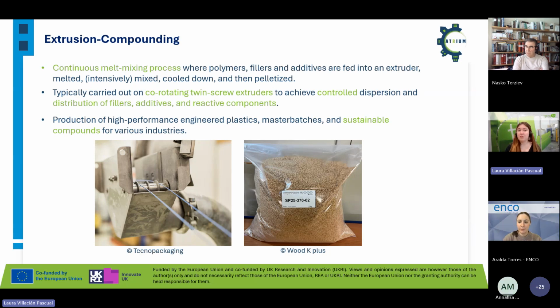So a little introduction to extrusion compounding. Extrusion compounding is a continuous melt mixing process where we have polymers, fillers, and any additive that you can imagine. And those are fed into an extruder, afterwards melted by applying heat, and intensively mixed through the screw. Once the polymer has been mixed, we cool it down, and then we pelletize, as you can see here in the picture on the right.